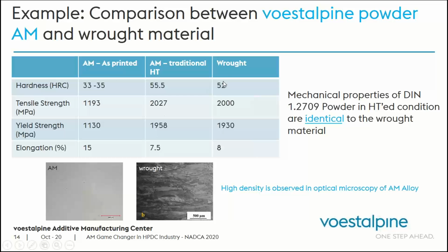If you look on this table on the right-hand side, if you buy wrought steel for the DIN 1.2709, its hardness is up to 52 Rockwell, the tensile is 2000, the yield is 1930, and the elongation is 8. If you build it by additive manufacturing, that's what we did internally, as printed you can get it to a certain hardness and certain mechanical properties, and going through the heat treatment cycle recommended for this powder, you can get it to 55 Rockwell, almost identical to the wrought steel.